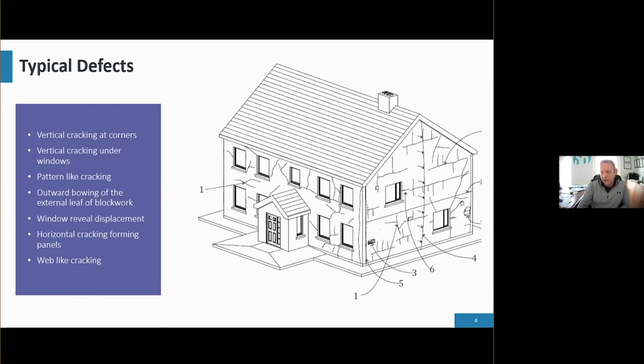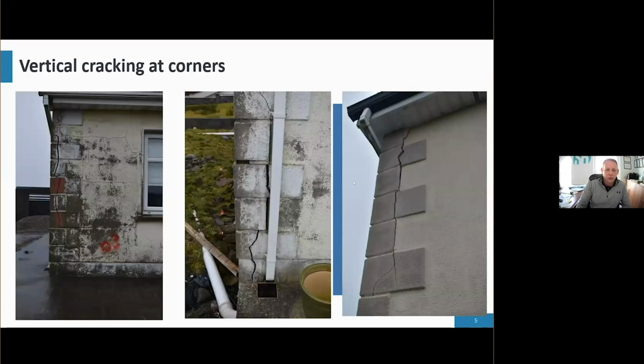Horizontal cracking forming panels, so we end up with these grids or panels, particularly on gable walls, but not necessarily always. And web-like cracking, which is essentially spider's web type cracking. So I've put up a couple of photographs to show people some samples of things we've seen. These aren't always the worst, and they're not always the most significant. Obviously, the extent of deterioration is only a point in time. These larger cracks that you're looking at here on corners weren't always that wide. So there is a progression of cracking throughout time, particularly with more exposure to the elements.